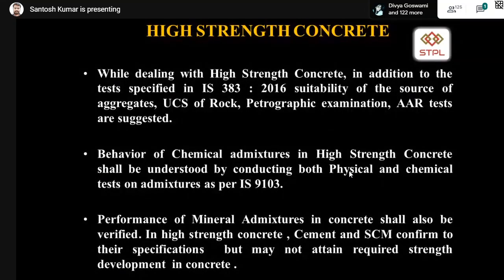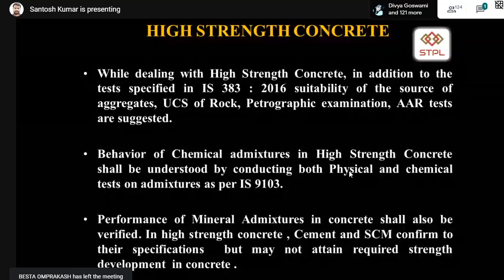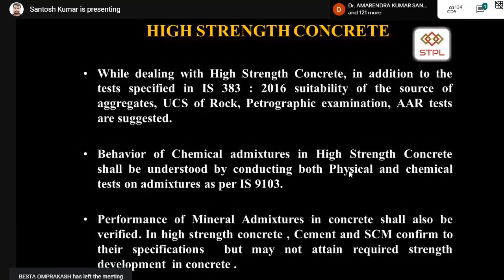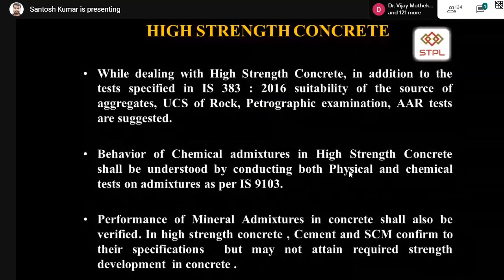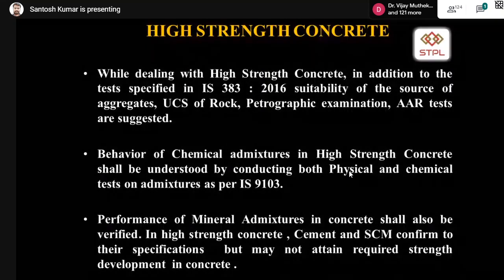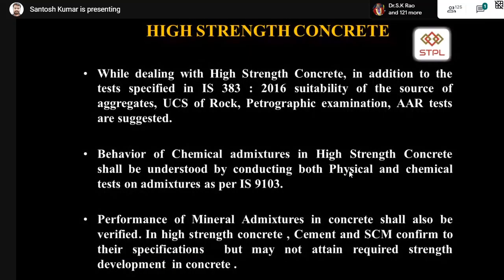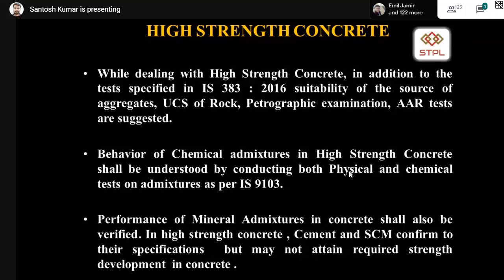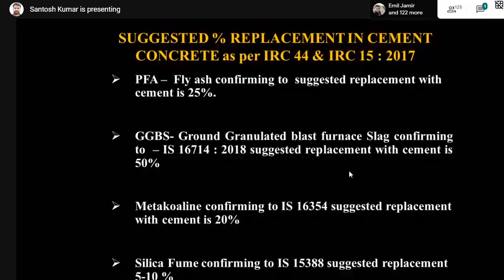So we should understand properly how the materials are behaving and what is the water cement ratio to be adopted. Because cement test is done at a particular consistency value and a particular amount of water is added. But in concrete, you don't have control on water. That means the water cement ratio may vary based on the aggregate temperatures, aggregate absorption corrections, admixture dosages. So it should be understood by doing the trials only.